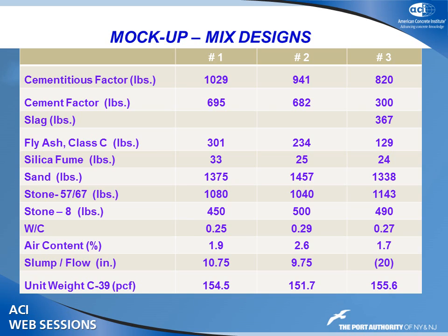And before we accepted a mix design, we said to the concrete contractor, you must cast a block. We know there's a lot of programs out there that can predict the temperature of the concrete. We want you to demonstrate to us what the temperature of this concrete is. Why? Because the shear walls in the core of this tower were as thick as 6 feet.